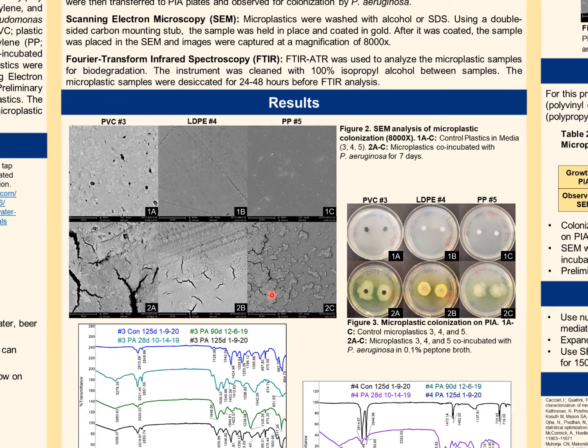Figure 2 shows SEM analysis of microplastic colonization. As we can see here, the top row is our control plastic and the bottom is our co-incubated microplastics with Pseudomonas aeruginosa for 7 days. We can see that there's a biofilm formed at the bottom row, which, when dried, form these cracks. We also see bacilli structures, which confirm the presence of our Pseudomonas aeruginosa.